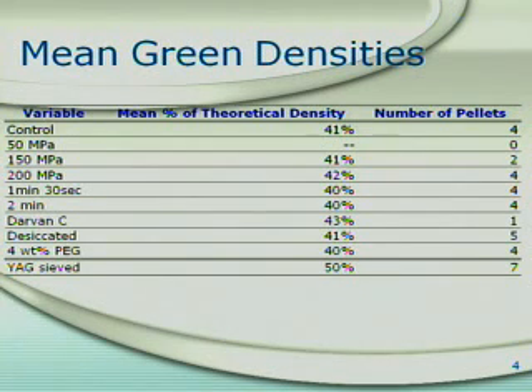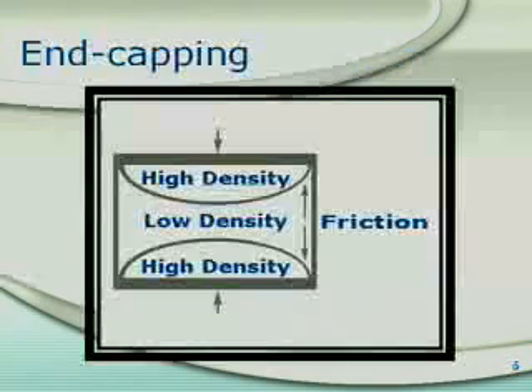After taking density measurements of the pellets at various steps, I used a student's t-test to determine if these results were statistically significant, and the use of more pressure in the uniaxial pressing stage and the use of Darvan C showed a significant increase in densities. However, as you can see in the table, these green densities are less than the 60% required. The amount of uniaxial pressure used to create the pellets with the highest densities in my study was 200 megapascals, which is enough to cause end capping of the pellets.